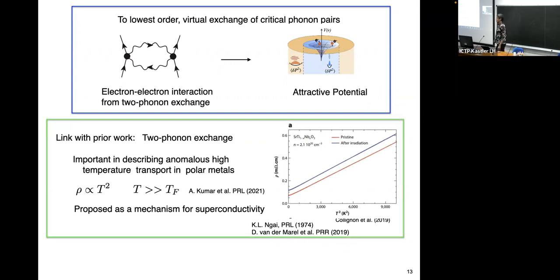Okay, so link with prior work. This two phonon exchange, first of all, Abhishek and Dmitri were able to solve a rather outstanding puzzle in strontium titanate using this two phonon exchange. We have a resistivity that goes like T squared. Recall that Malta mentioned a T squared yesterday. Now you might say, what's the big deal? The problem is the Fermi temperature is something like 10 degrees and T is going all the way up. So why is it still T squared even though it's in the classical regime? Abhishek and Dmitri and their collaborators actually showed that with this two phonon exchange, you can explain that.